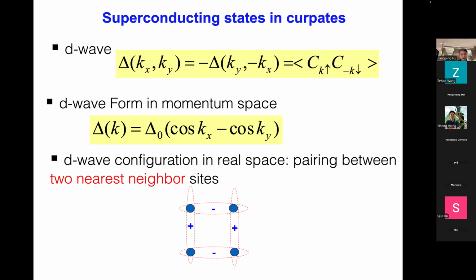The pairing symmetry is one of the most important characteristics of the superconducting state. Typically, we have some conventional superconductors that are S-wave superconductors. Another, different example is the D-wave superconductor, the cuprates. These are another class of high temperature superconductors, and we now know they are D-wave. D-wave means that for the order parameter, you rotate 90 degrees and you get a minus sign.